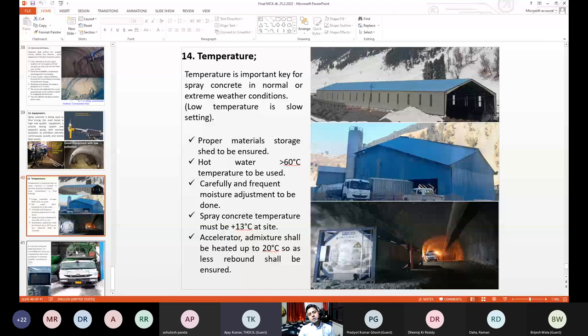Hot water should be more than 60 degrees centigrade temperature, to be used carefully, and frequent moisture adjustment to be done regularly. Spray concrete temperature must be plus 13 degrees centigrade at site. Accelerator admixture shall be heated up to 20 degrees centigrade so as less rebound shall be ensured.